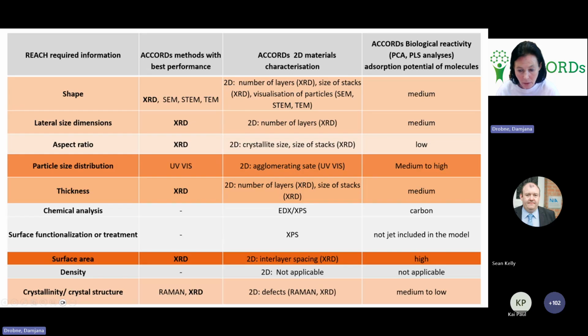About chemical analysis, in case of iCARE, we talk about carbon-based materials in all cases, but when we compare this to vaccines, of course, that's a little bit different chemical composition. Also, in our case, we had some functional groups, but they are not included in this model yet. And the highest contribution to reactivity was the surface area, which we translate or adopt to the material as interlayer spacing. Density, we think, is not applicable. And crystallinity and crystal structure, we think the best in 2D materials would be defects. We are not sure yet. It's a matter of discussion, finalizing the project and all the results.